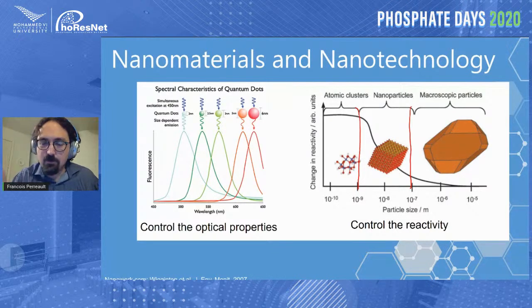And you can see that when you go below that 100 nanometer range, surface reactivity and surface property really start to pick up very quickly, because below that range you start to get a much higher proportion of atoms at the surface of the particle that become available for surface interaction. So nanotechnology is really about controlling these surface properties that become dominant compared to bulk properties when you get to these very, very small sizes. So that 1 to 100 nanometer size range is not completely arbitrary, but what's more important is the unique properties that emerge at this size range.